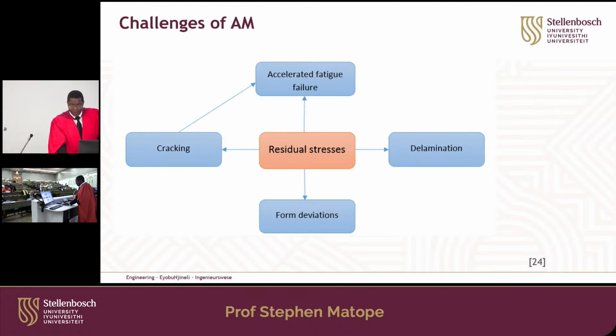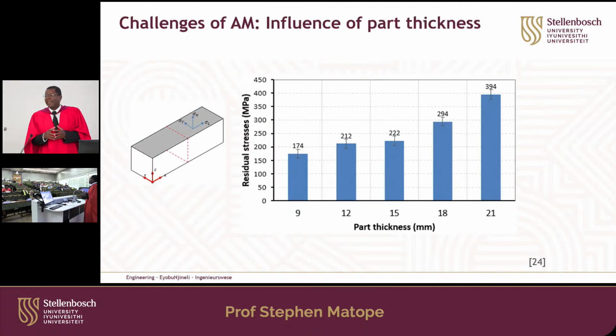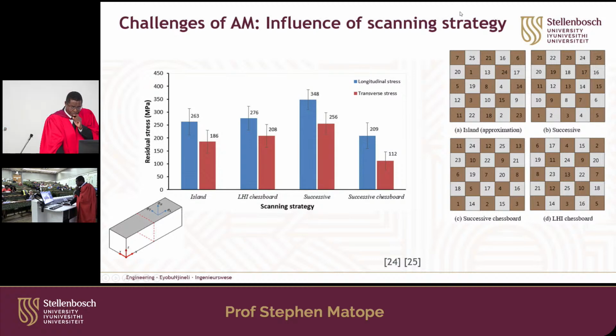But I'm happy that one of my students worked on this research and looked at the influence of part thickness. We found that the thicker the part, the higher the residual stresses. So by all means, try to keep the part thickness quite low. That's why we did not make the whole tube by 3D printing. It was only that final part where we wanted faster heat transfer, which we then printed using 3D printing additive manufacturing.